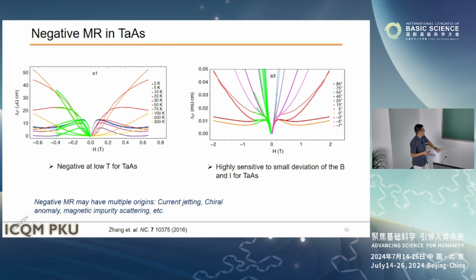So we did some measurements, like longitudinal magnetoresistance measurement. This is resistance versus magnetic field. To some extent, at a certain temperature range and a certain magnetic field range, we found some negative magnetoresistance. However, we noticed the negative magnetoresistance may have different origins. For example, if your compound has a very high mobility, your current may be disturbed by the magnetic field. At that point, you also observe the negative magnetoresistance. That's what's called a current jetting effect.